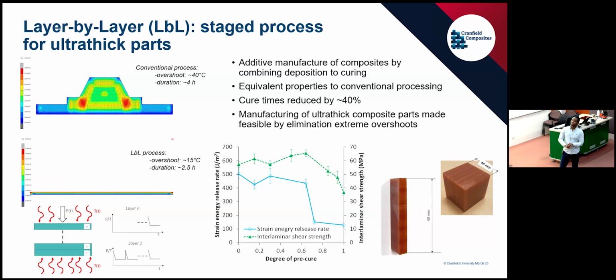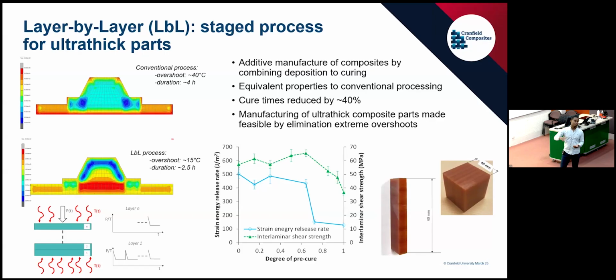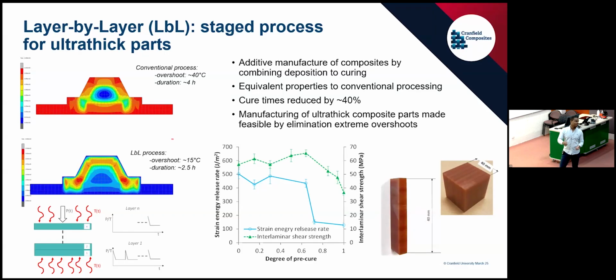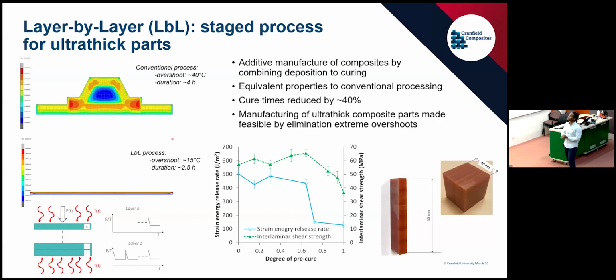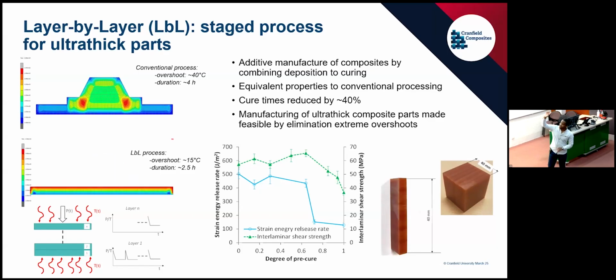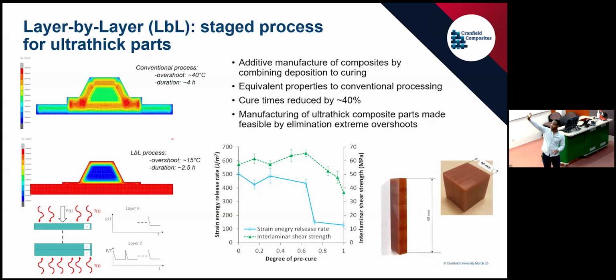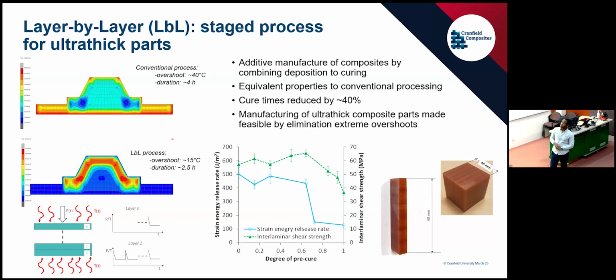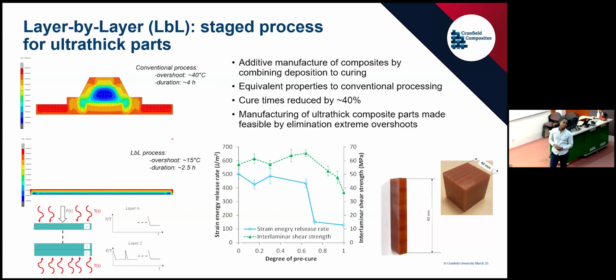So loads of process science here on the adhesion between the layers, getting everything to cure sensibly. So you don't take it all the way to full cure. You cure it to about 25% till it's stiff enough. And then you can do a post-cure in the oven after, but you can vary that quite a lot. And loads of work obviously done on the process simulation of this as well. And this is one of these techniques that we really hope to carry over into ceramic matrix composites, which is a great area of collaboration I think we can have with UniSQ.